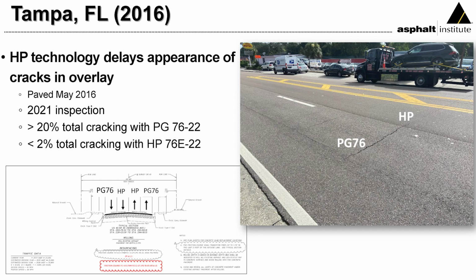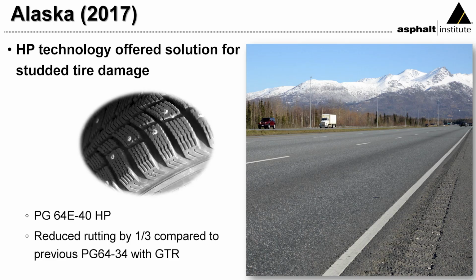In Tampa, Florida, they built these sections as an experiment for reflective cracking. And when they measured it after several years, they were seeing a substantial improvement, over 20% total cracking with their standard PG76-22, and less than 2% total cracking with the HP 76E-22. So again, that reflective cracking seems to be delayed significantly by this technology.